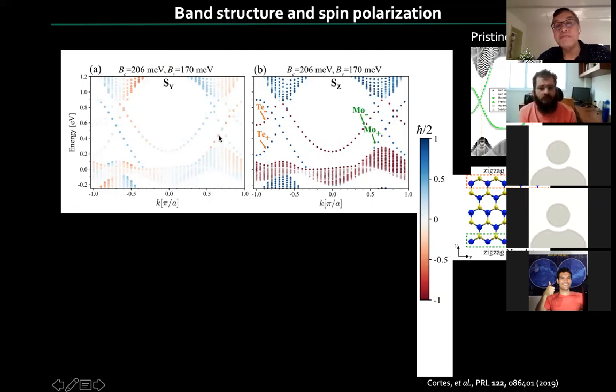Now, there are two panels here, because in addition to the exchange bias that is mostly in the Z direction, right? By the way, here on the upper right, I have the cartoon of the pristine ribbon without the exchange bias. And of course, here you have the four states, but they're all together because the only split is the spin orbit. But here I have a combination of spin orbit, the magnetic biasing, the exchange, and also a Rashba field, because now I've broken the symmetry even further, and that creates a Rashba field. So the spin gets shifted not only in the Z direction, if you will, but in another direction given by this Rashba field, which here is called Y. The fact that these symbols are dimmer than on the right is because most of the spin still points in the Z direction, but it's simply tilted with this Y.